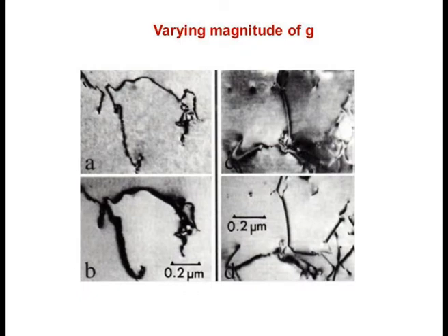Similarly, the same dislocations which are imaged with different types of G vectors, similar to s, you can see that the contrast is varying. See here, this looks like this dislocation is cutting for this G vector which I had chosen. Another G vector, you see that it's not cutting. Here, with another G vector, it looks as if they are touching each other, here it does not. It's the same area of the sample. So what do you interpret? If you take only this picture, we say that there are two dislocations. If you look at this picture, what will you say?